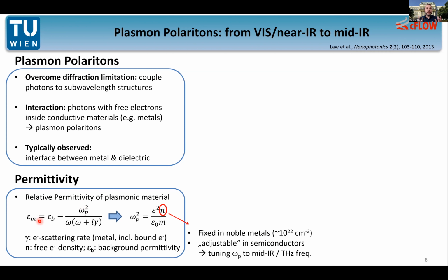So we have not much room to play with it, let's say. This is different in semiconductors, because in semiconductors, as you will know, we can dope them, so we can really change the amount and the density of free carriers significantly by really multiple orders of magnitude. And by this, we can tune the plasma frequency to mid-infrared and infrared spectral range. So this gives us an additional degree of freedom to really address a specific wavelength that we want to have.